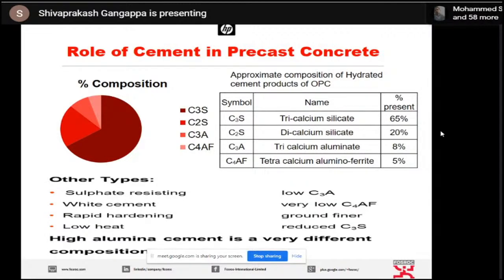Performance, is it with respect to your compressive strength, or is it with respect to your durability of concrete? So how do you get high strength? The moment you get a high strength, the performance automatically goes better. That means if you do a chloride penetration test, for example, a rapid chloride penetration test or a rapid chloride migration test, or if you do a pressure test using DIN 1048, which is a German standard, in all cases, the high strength concrete, which is more dense in nature, exhibits a better resistance to water penetration. The moment water penetration goes better, automatically what happens? It gives a better life of the concrete, which increases the performance.